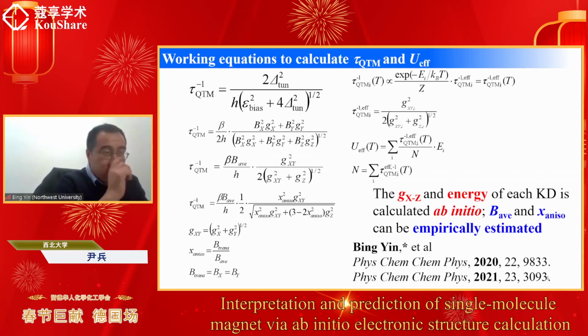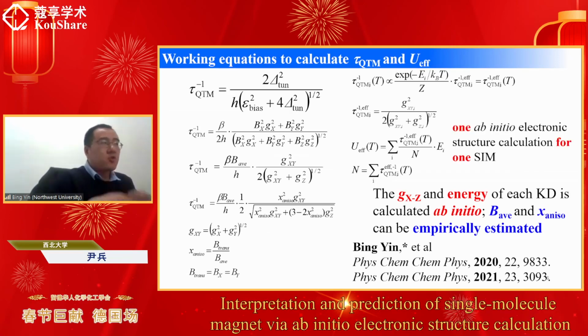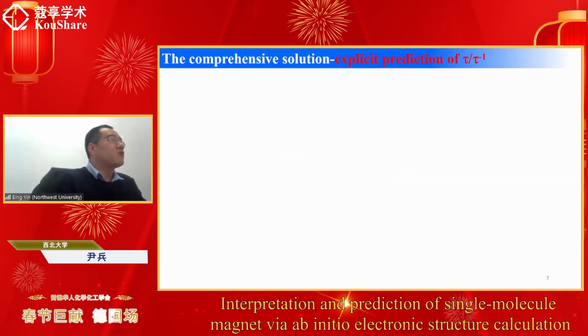And these values can be calculated from ab initio results. And the other type of parameters describes the internal magnetic field felt by the system, as well as the anisotropy of the magnetic field. These parameters cannot be calculated directly from ab initio results, but they can be empirically estimated. So, in the ideal case, for one single-ion magnetic system, only one ab initio electronic structure is needed to give reliable prediction and interpretation. Of course, I have to admit that there are other methods that are more comprehensive and more accurate than the one proposed by us.